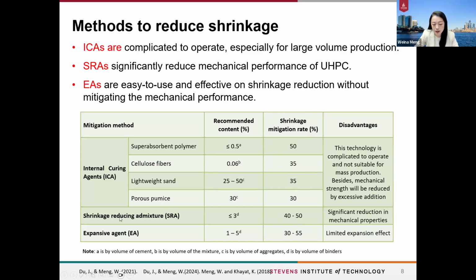And for the shrinkage reducing admixtures, even though it is very effective in reducing shrinkage, it is reported to have an adverse effect on the mechanical properties, or reduce the mechanical properties. So compared with the other two methods, using expansive agents is an easy-to-use method, and it can reduce the shrinkage a lot without compromising the mechanical performance.